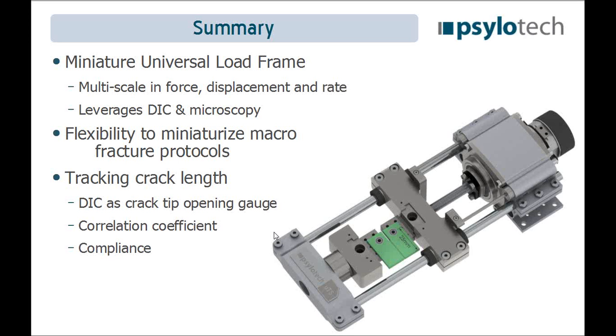Of course, the key to this is digital image correlation and using microscopy to obtain the images. I also mentioned 3 ways that you can use the system and DIC to track crack length. You can use DIC as a crack tip opening gauge. You can use a correlation coefficient to indicate where the crack is on the surface. And the last way is using the high resolution technology unique to Psylotech to track compliance.